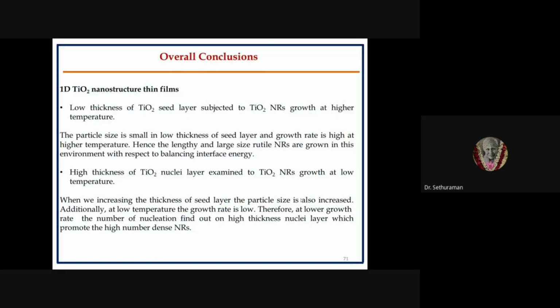So, overall conclusions: for one-dimensional TiO2 nanostructure thin films, a lower thickness of TiO2 seed layer was subjected to TiO2 nano growth at high temperature. A high thickness seed layer was used for growth at lower temperature. At high temperature with a lower thickness seed layer, the particle size is small, so the growth rate is high. That is the reason lengthy, large-size nanorods are grown.